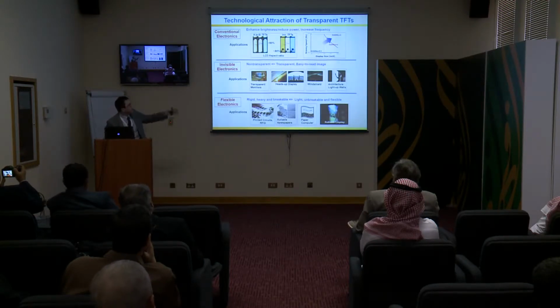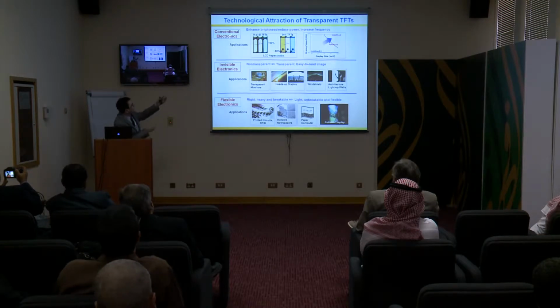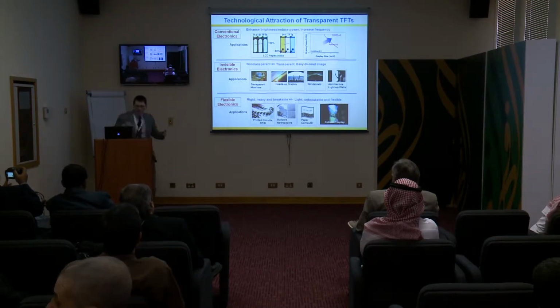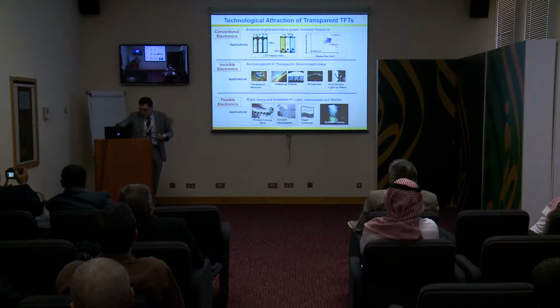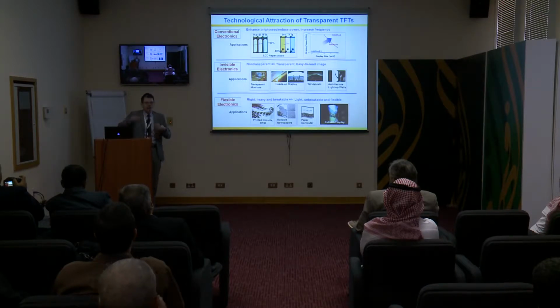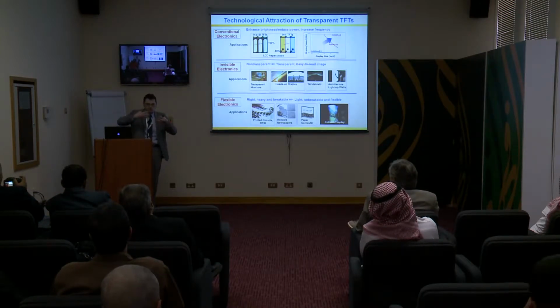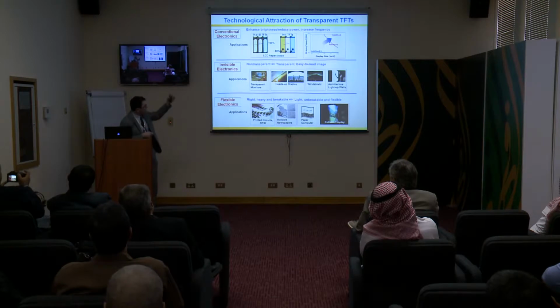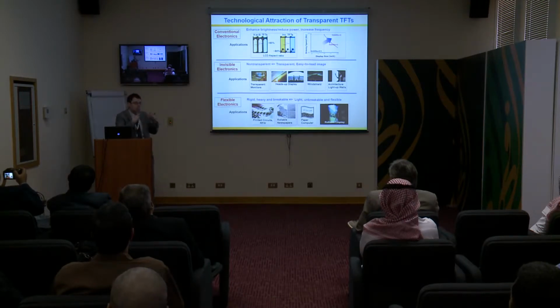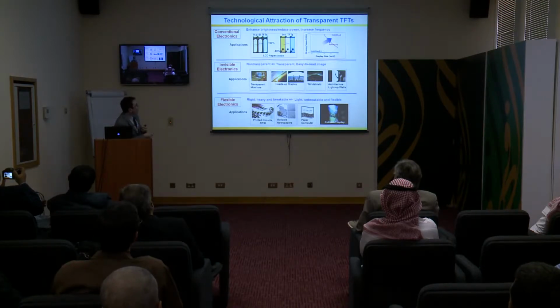And people have been looking at this material in conventional electronics, for example, in this TFT, you actually see the stripes, right? You see the single pixel because the amorphous silicon is optically opaque. And this takes away some of the light from the back of the display. So you have what is called aperture ratio, which suffers because the silicon is opaque. But if your TFT would be transparent, you would save a lot of energy because this light goes through. So this is one of the applications of metal oxide.